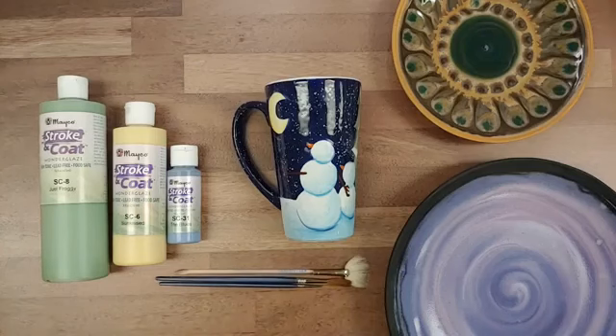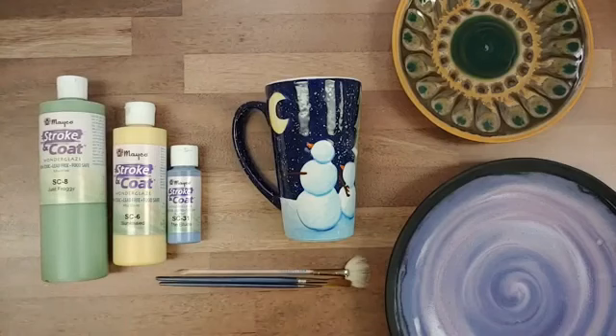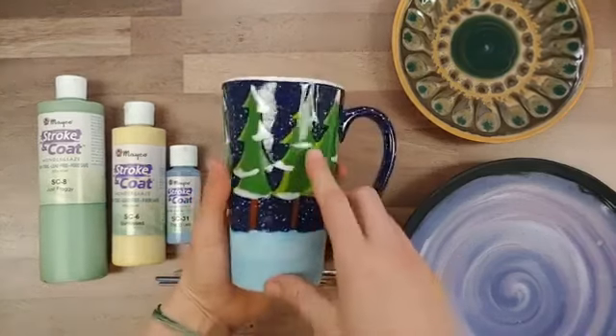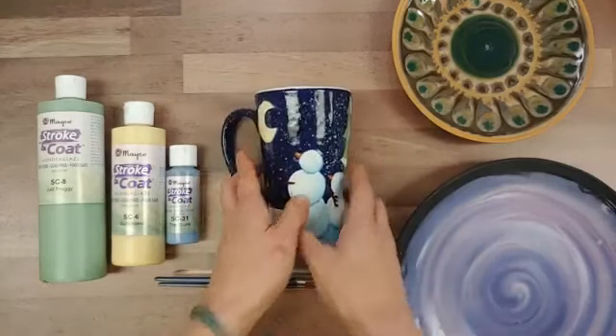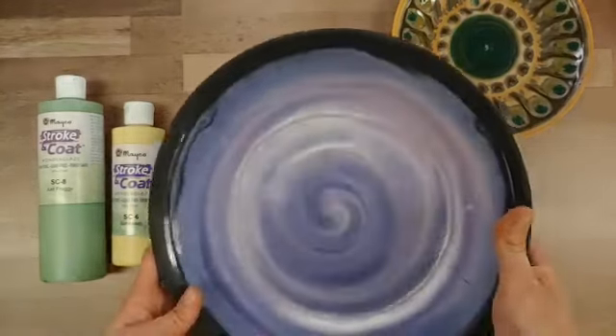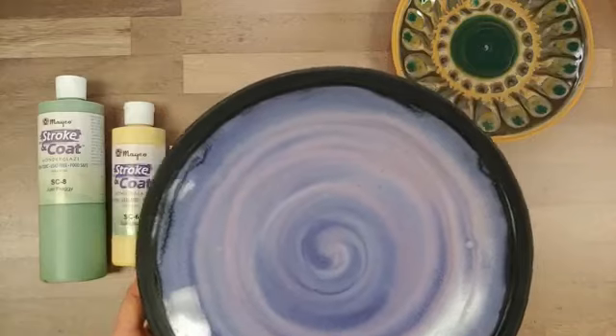For our mid-range products we have cone 6 and cone 10 available, just to give you more information on how these products perform. Strokecoat holds up great at cone 6, and a lot of the colors even look good at cone 10. However, when bringing it up to higher temperatures you're not going to get crisp, clean line work like you do at low fire. If you're using it at higher temperatures, I'd recommend using it in layering with other glazes — for example, Strokecoat layered over Alabaster, like Fruit of the Vine over Alabaster, to bring colors you might not normally have in your stoneware palette.